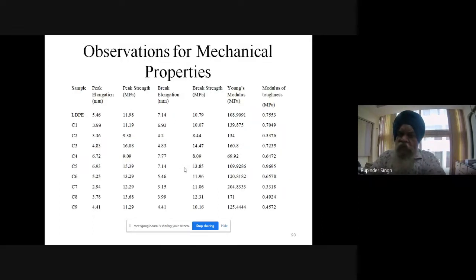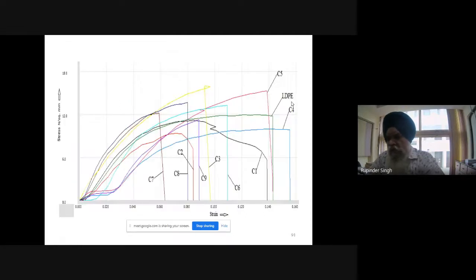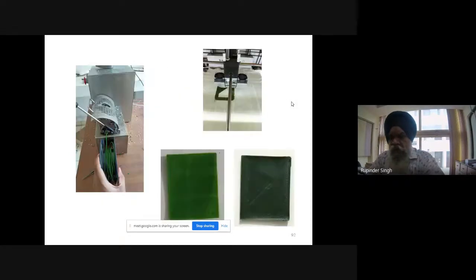So we tried different processing conditions on my extruder, and we tried to see the effect of the processing condition on the peak elongation, peak strength, break elongation, break strength, Young's modulus, and modulus of toughness, these types of properties. This is a typical stress-strain curve we get for this type of material.